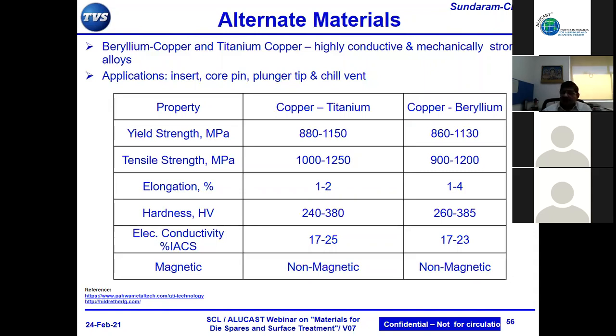In terms of thermal, improving the thermal balance in the die, beryllium copper, which was quite popular, now titanium copper materials are coming, which have been becoming more and more popular these days, which are highly conductive. At the same time, they are mechanically strong. Titanium is very strong, and it could really help in good thermal conductivity, and at the same time look at not getting reacted with aluminum.